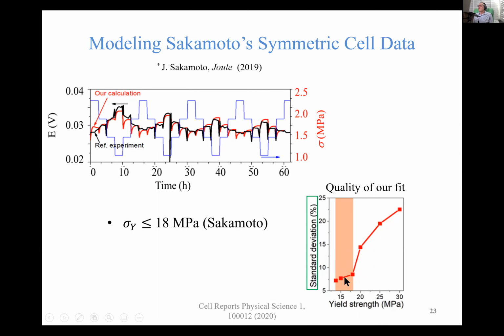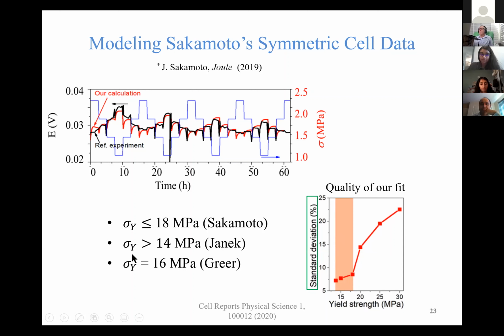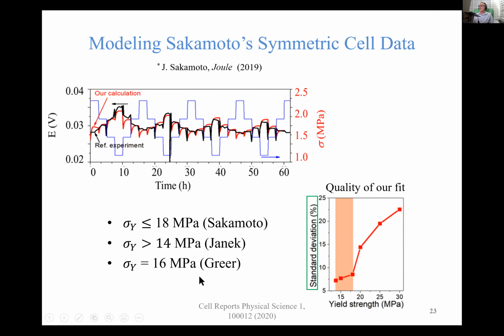And so in order to put Sakamoto's data in harmony with our model, we need a yield strength below 18. Now, you may remember a few slides ago that I said in order for Janek's data to make any sense at all, the yield strength had to be at least 14. And then just in the last few months, Julia Greer published some data where she measured the yield strength to be 16 megapascals. And so we are sort of getting to a consensus of what the effective yield strength is. Remember, effective means that the yield strength can vary from point to point, but it's acting as though the overall yield strength were very close to 16.